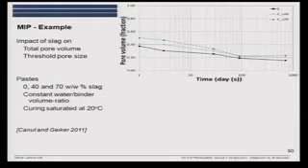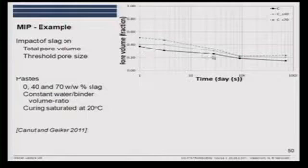And it's pastes with no slag, and 40% and 70% slag. And we have a constant water to binder volume initially, and the samples were cured at 20 degrees and saturated. And here you see the variation in pore volume as a function of time. And what you see initially, after one day, less of the slag has hydrated, so we have a larger volume of pores. And even at 800 days, we have a larger volume of pores.